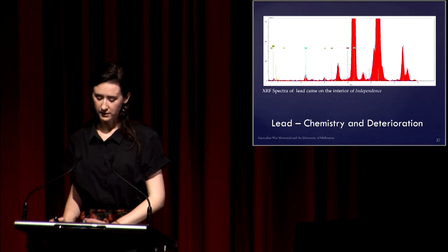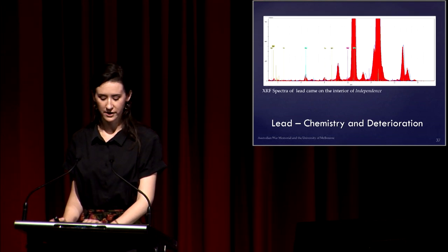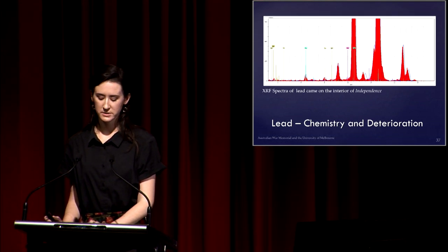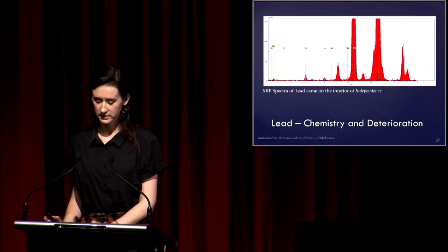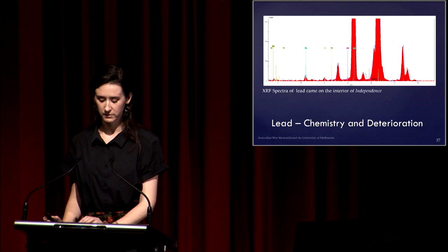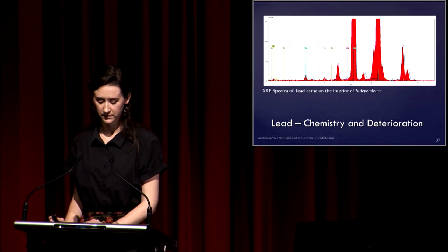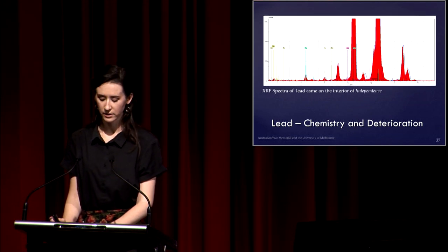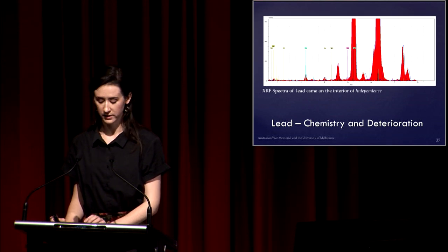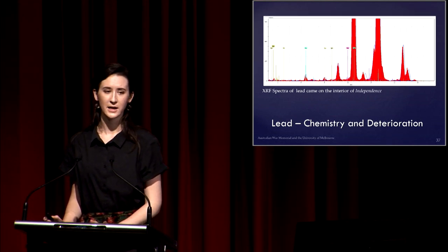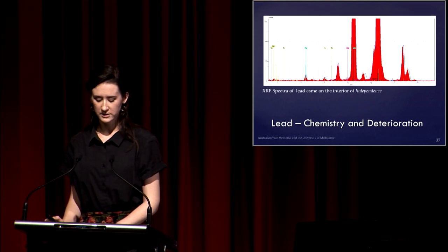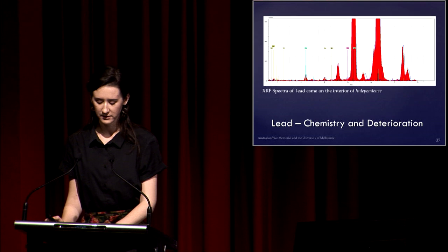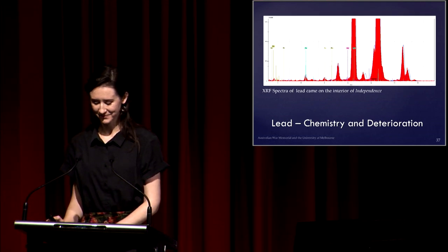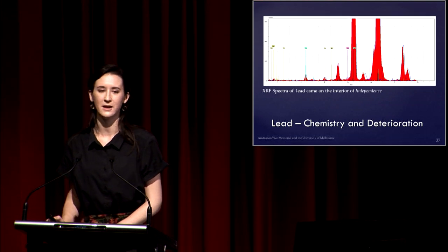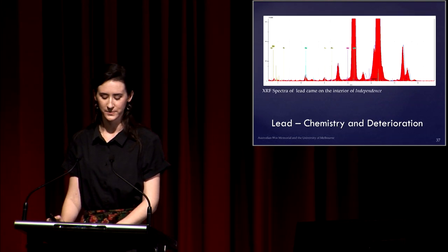So we analysed the metallurgy of the leads in our windows with XRF. XRF identifies materials by emitting high energy light that causes distinctive X-ray emissions to be produced by each element that is then reflected and received by the instrument. We found that the leads contain trace elements of copper, tin, antimony, and silver. The trace elements identified greatly enhance the durability of the leads, and the composition is actually akin to current standards for conservation grade lead, which is really good news for us. It means that they could be expected to last up to 200 years before they require replacement.